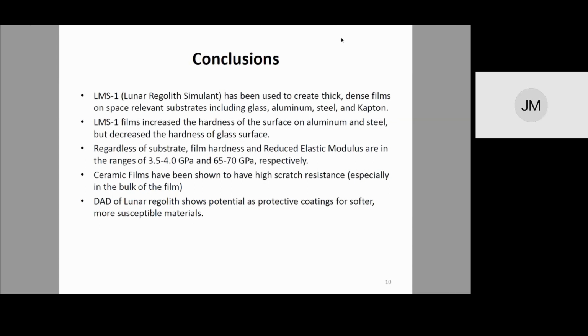A couple conclusions from this. We used LMS1 to create thick, dense films on space-relevant substrates, including glass, aluminum, steel, and Kapton. The films increased the hardness of the surface on the aluminum and the steel, but decreased the hardness of the glass surface. The film hardness, regardless of the substrate, and the reduced elastic modulus are in the ranges of 3.5 to 4 gigapascals and 65 to 70 gigapascals, respectively.